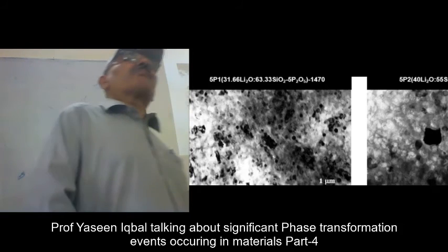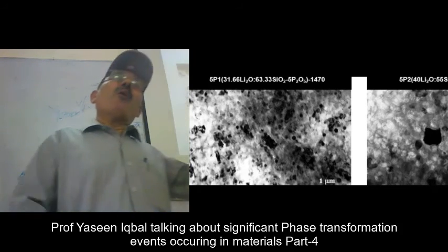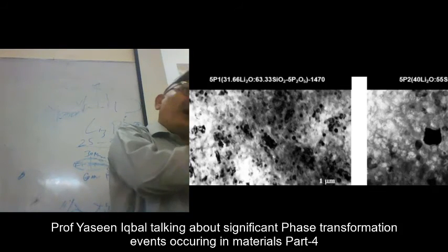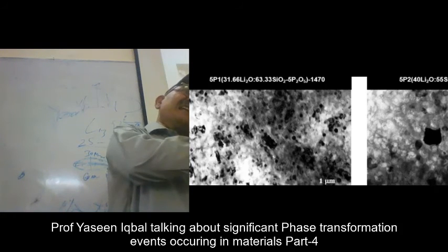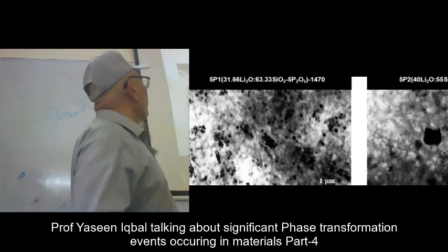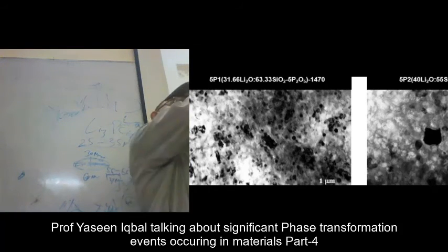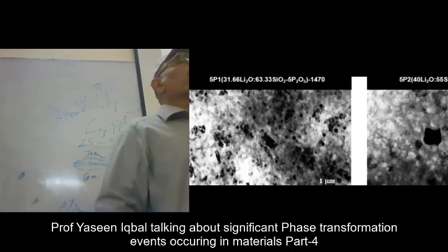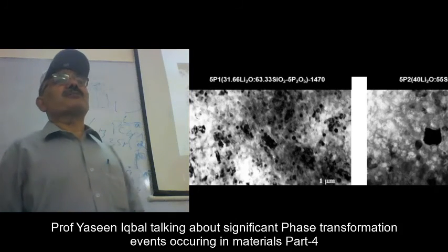It has some crystallographic plane where the lithium disilicate sits very well with ease. When that ease is provided, lithium disilicate material comes and sits on that plane preferentially and multiplies, increasing the nucleation rate of the material.